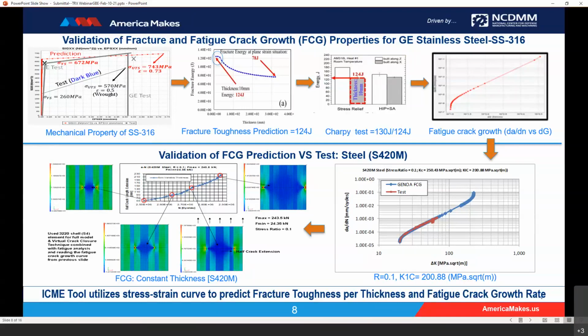The image on the far right is the prediction for fatigue crack growth rate. We can have confidence in this approach based on the validated results achieved with S420M steel below. As you can see, the image on the lower right is that fatigue crack growth rate prediction compared to test. And so we had very good agreement with test, and we're able to not only see the curve, but actually compare it to points of crack growth on a physical panel.